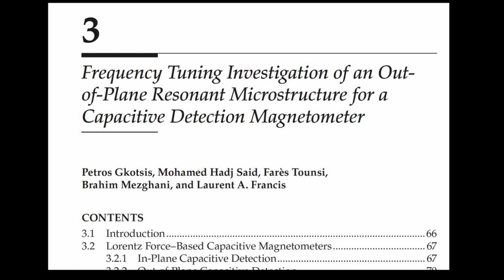Modeling shows frequency increases linearly with DC voltage at low vibration amplitudes, but nonlinearities reduce tuning effectiveness at higher amplitudes. Experimental validation confirms frequency shifts up to 38% at low currents with DC bias, providing a feedback mechanism to stabilize frequency and improve sensor performance. It's a neat way to maintain sensitivity and stability without complex external controls.